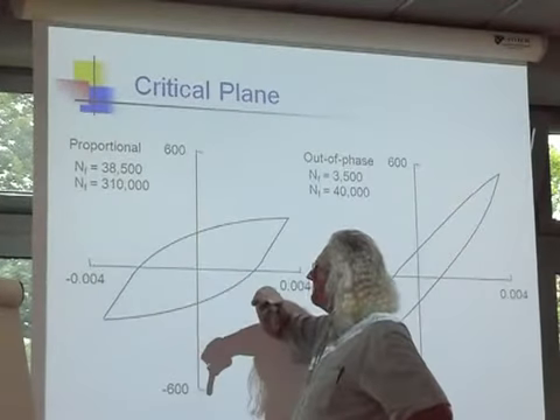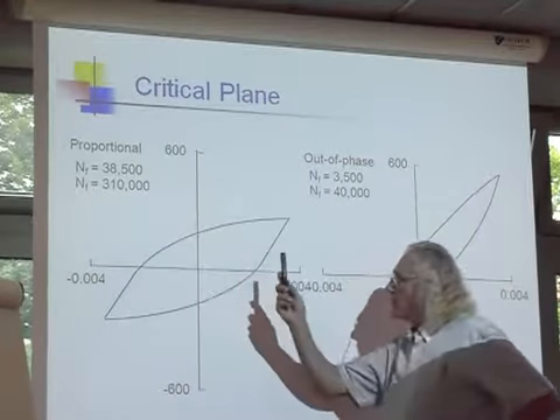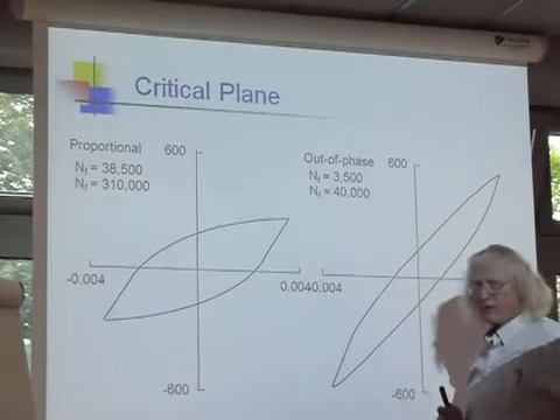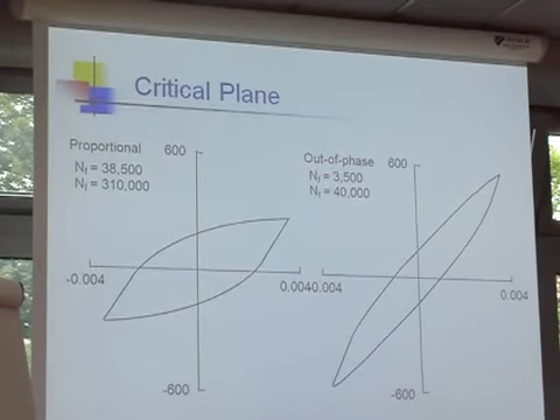And by the way, if we do it at a lower stress level, of course, the lifetime is longer, but we compare the value of 310,000 with the value of about 40,000. And so, again, our factor of 10.